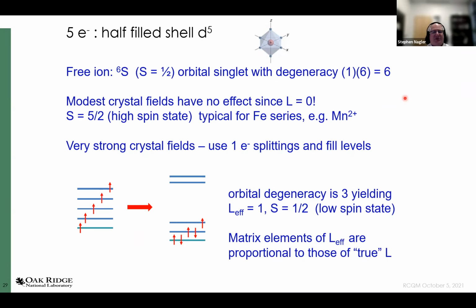And this is sort of typical for d5 electron systems in the iron series, like manganese 2+. But if I have basically larger ions, like say iridium 4+, where the electrons have a much bigger radius, there's a much larger perturbation from the charges from the surrounding ions, and the crystal fields can overwhelm Hund's rules. And then I imagine I have large splittings and I fill up these levels in accordance with Hund's rules.